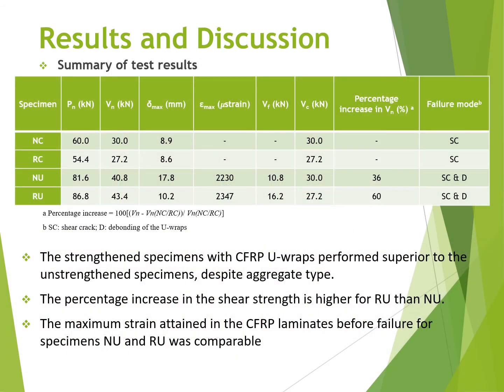Moving on to the summary of test results, this table shows the summary in terms of the maximum attained load, which is Pn, maximum shear force, calculated by statics as Pn over 2, the midspan deflection at maximum shear force, the maximum strain attained in CFRP laminates, the shear in the concrete, and the FRP contribution to shear capacity, which is V sub F, and the observed failure modes.